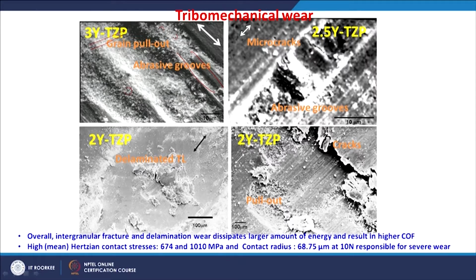When the yttria content was reduced to 2.5, again you can see the abrasion grooves and also certain micro cracks. But when the yttria content was reduced to even lower levels of 2 mole %, there is a change. Here you can see the delaminated tribo layer, and in addition to this delaminated tribo layer, there are certain cracks and also pullout of the material. So, overall we can say intergranular fracture and delamination wear. These dissipate a larger amount of energy, so you get a larger coefficient of friction and wear.